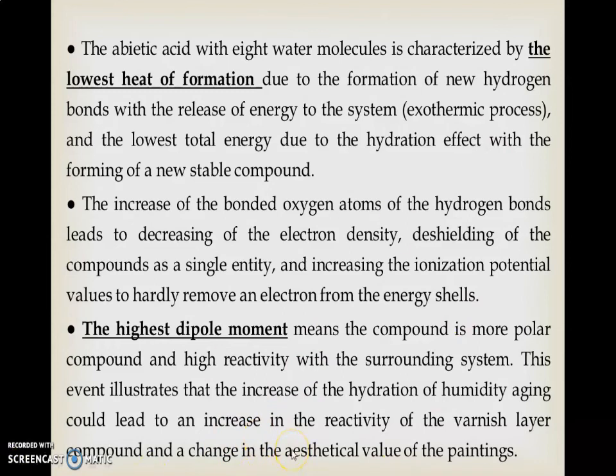Also, upon fluctuation of the environmental conditions, these bonds break to induce physicochemical interactions and deterioration and degradation of the materials through peeling and growth of microorganisms. So optimization of the different environmental conditions is very important, and it is recommended to keep relative humidity less than 85% to avoid the damage risk to the painting materials, and to use calibrated devices to monitor the readings of the temperature and the relative humidity.